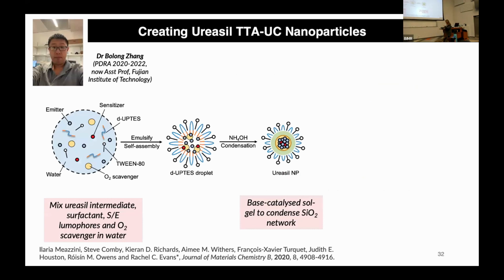So Bolong was a postdoc in my group, and he had seen one of our earlier papers where we'd made these ureasil nanoparticles, and he thought, well, this would be great for TTAUC. So he prepared our system, he modified the synthesis slightly. So we now have our sensitizer and our emitter. We have our ureasil precursor d-UPTES. We have some Tween just to act as basically an emulsifying agent to stabilize the surface. We throw in an oxygen scavenger to try and reduce the problems of triplet quenching.